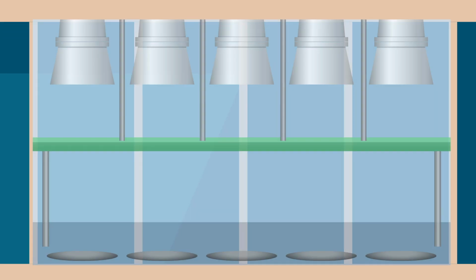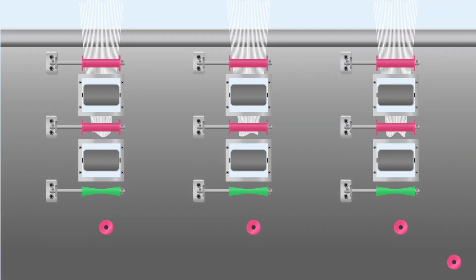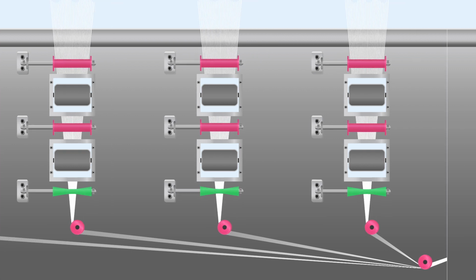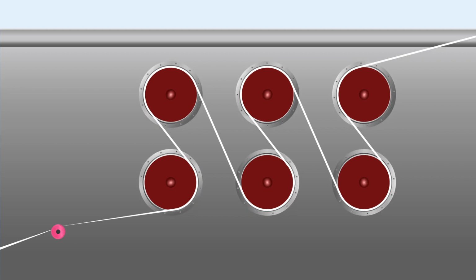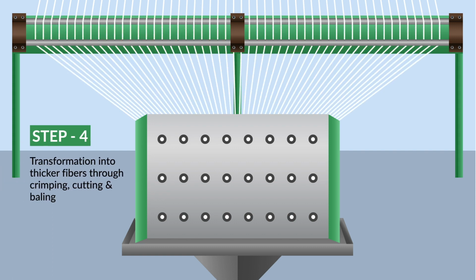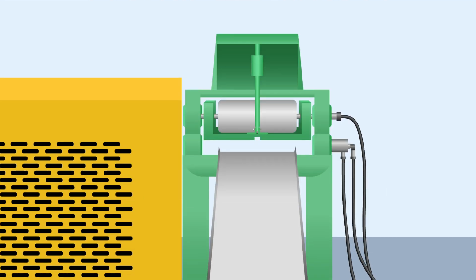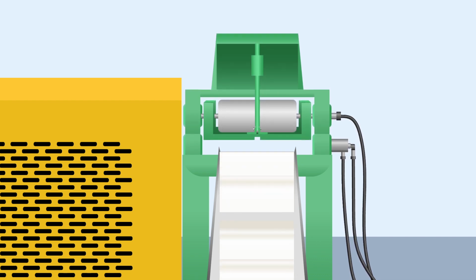The molten liquid is now passed through spinnerets to create multiple minute filaments, which are passed through the take-up area where multiple filaments from all the spinnerets combine to form a tow and are collected in a can. Tows from multiple cans now pass through the guide frame from where it is sent to the draw frame. Next process involves use of multiple tows that are passed through different sized cylindrical rollers. These are now allowed to pass through annealer rolls where heat setting takes place. The resultant tows undergo crimping, get dried and cut into the desired fiber length and get packed in bales of